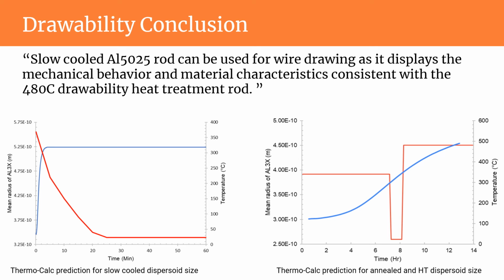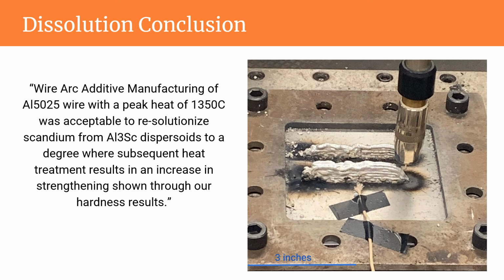The team concluded that slow-cooled aluminum 5025 rod could be used for wire drawing, as it displays the mechanical behavior and material characteristics consistent with the previously drawable thermally processed rod. Additionally, we concluded that WAM of aluminum 5025 wire with a peak heat of 1,350 degrees Celsius was acceptable to resolutionize scandium from Al3Sc dispersoids to a degree where subsequent heat treatment results in an increase in strengthening, shown through our hardness results.